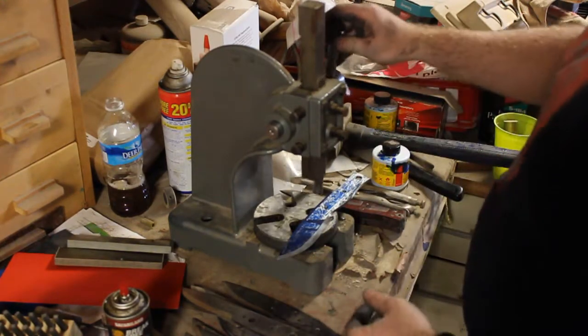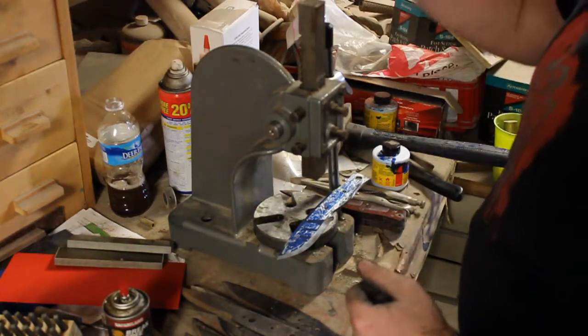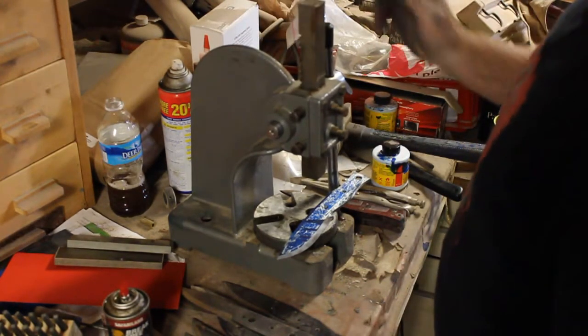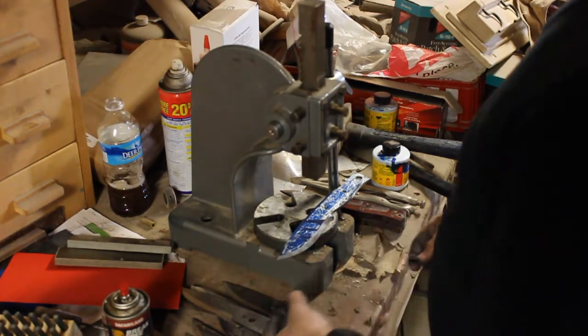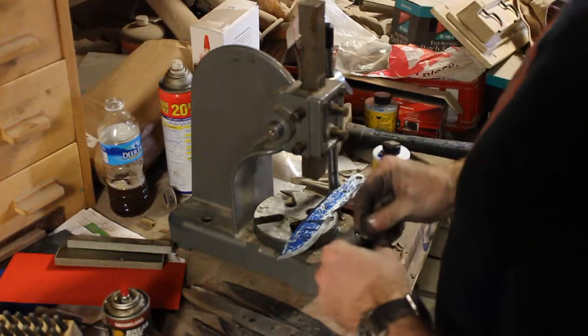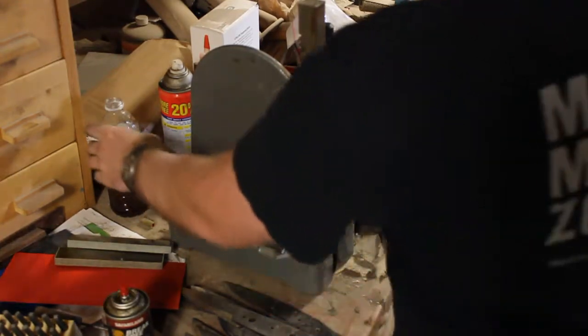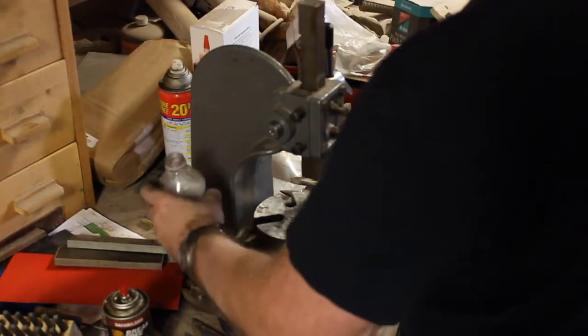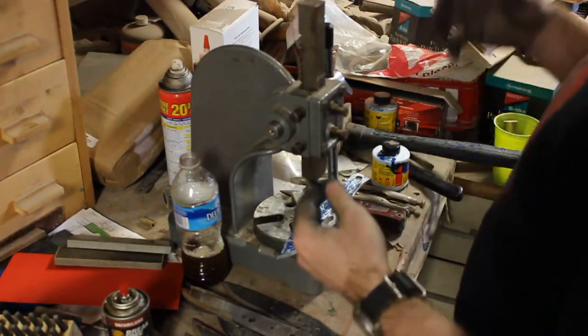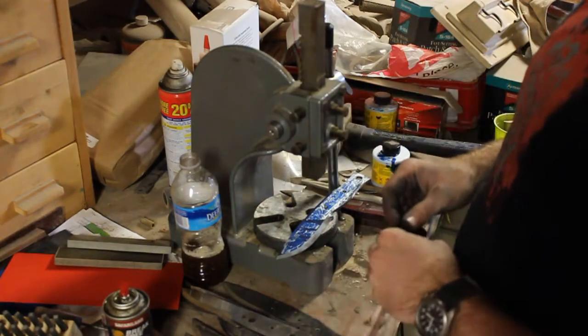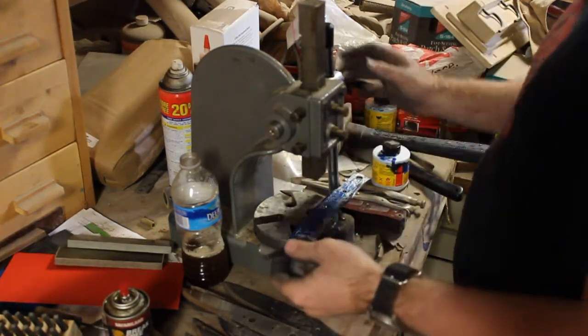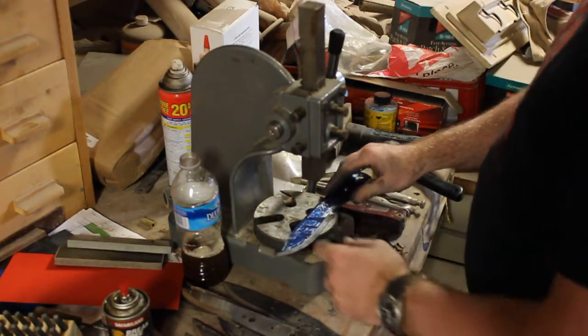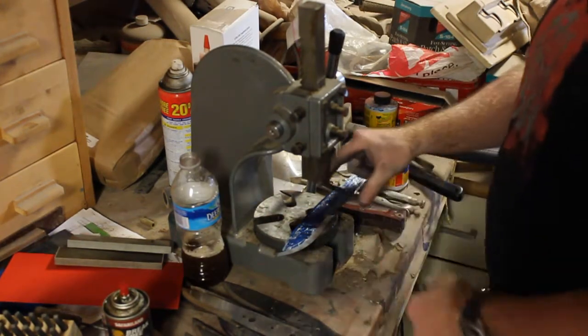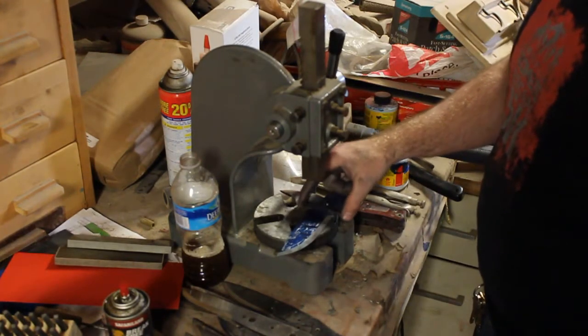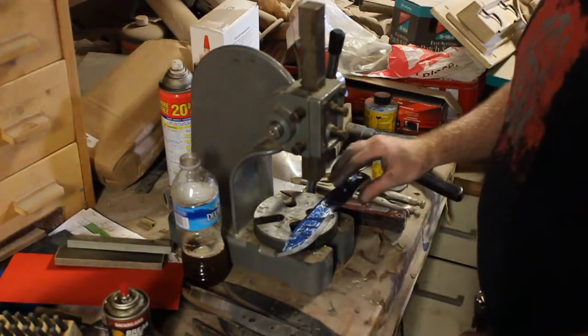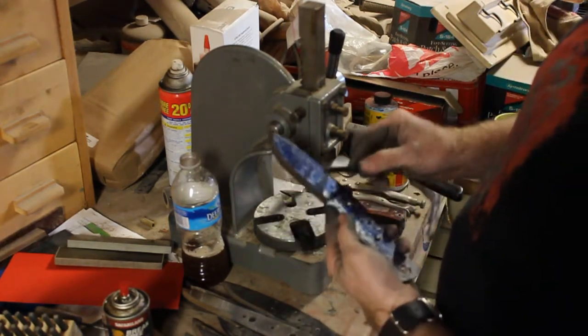So, the way that I run my stamps, I use this cheapo Harbor Freight arbor press and these steel stamps. And we start out with a C, and I don't like to get them too close to the spine. I don't think it looks good, and then something in the back of my mind says it might cause a more serious stress riser. I don't know if any of that's true, but another thing that I do is I try to keep the stamp tip-wise of the plunge lines. The handles on this specific knife are going to come up to about here.